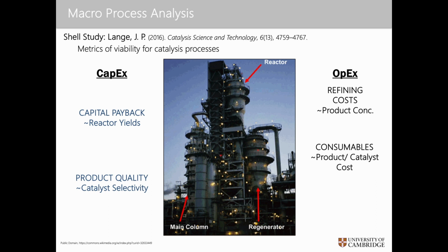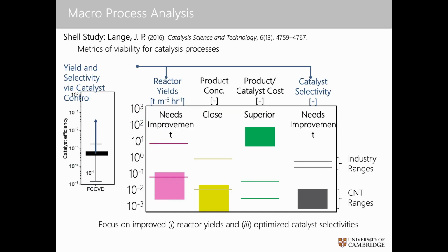And then the other is a consumable cost, which is basically your number of products over your catalyst, and you might scale that by cost as well. And so in our case, at least now, the product value you might think is very high, and the catalyst is relatively cheap. It's just iron with a bit of sulfur, and you might even use iron oxide, rust, as your input here. And so this is those metrics now put on the ranges that Lang found relative to the boxes, which are not just our own group's, but the world's CNT processes being produced. So what I would argue is that the most important for us to improve is reactor yields, where we're just slightly over the minimum threshold, but not often, frankly. It's only kind of specialized conditions that we're running, and we're often trading one factor off to get there.